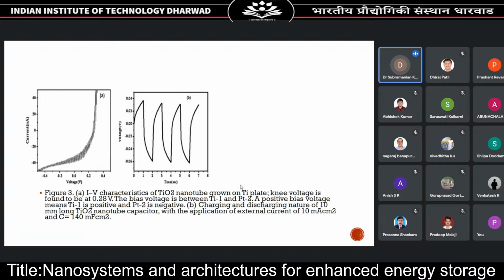Now figure B shows the storage behavior, which is galvanostatic voltage versus time. You can see that voltage rises to a maximum value in the charge sequence, then it discharges, and this cycle can be repeated for many cycles. We got a capacitance of 140 millifarads per centimeter square. It is a very small structure with titanium dioxide nanotubes, so even realizing 140 millifarads per centimeter square is a very good value for this storage structure.